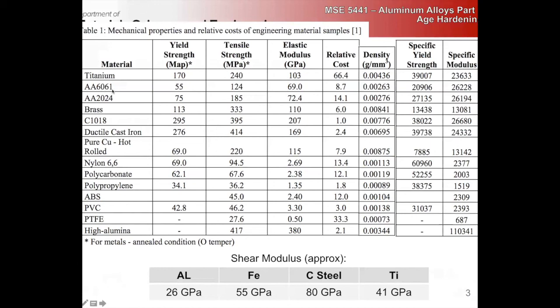6000 series aluminum, 6061. This is what your bike frame is made out of, right? So if we just look at it, we see the big changes in modulus versus steel, right? And the big thing is if we look at the specific moduli values, right, which is normalized by weight, aluminum actually does pretty good compared to our steel, right? Which is one of the reasons why we use aluminum so much, because in terms of specific strength, it's pretty strong.